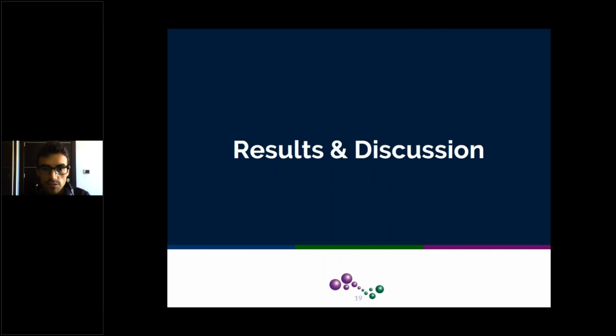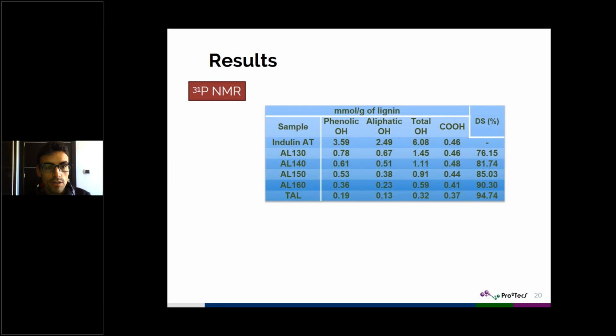Well, let's now start with the results and discussion. Well, first of all, I would like to show you the phosphorus NMR results. As you can see, the indulin AT has very high hydroxyl groups. So after the acetylation by microwave assisted acetylation, we can see that as we increase the temperature, we obtain less and less hydroxyl groups. In both cases, both for phenolic and aliphatic hydroxyl groups.